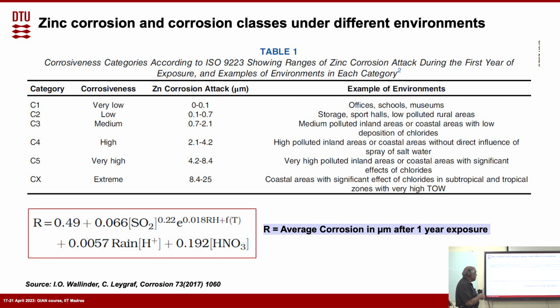This is also from the same studies, on zinc corrosion and corrosion classes under different environments. For example, zinc corrosion attack on the micrometer scale is shown here. They looked at different corrosion categories depending on where the zinc is placed. You can see 0 to 0.1, which is offices, schools, and museums, where it is internal. Coming from that to the CX condition, the extreme condition, there is about 8.4 to 25 micrometers of corrosion when you have very high chloride conditions and things like that.